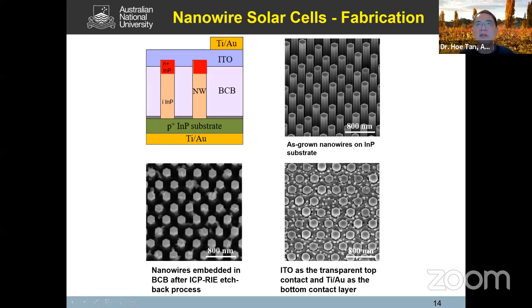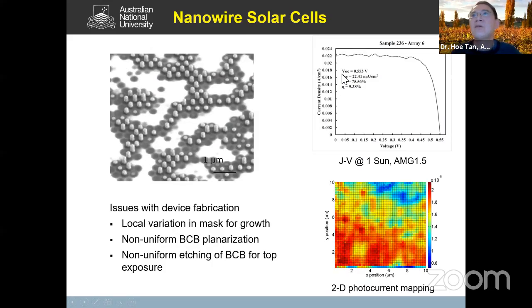So after that, we did our measurement for the nanowire solar cell. As you can see here, we got some photovoltaic action. So this is not great. You can see the efficiency is only just under 10%. You know, III-V nanowires typically have very high efficiency, but this is nothing to be proud of.